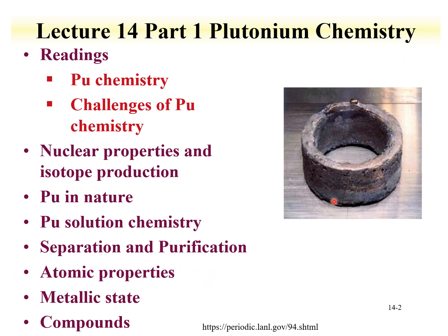And here we see an example of a ring of plutonium. This is made from an electrochemical process where you can form plutonium in a molten salt. The melting point of plutonium for a metal is relatively low. It can drip off the electrodes and form into rings.